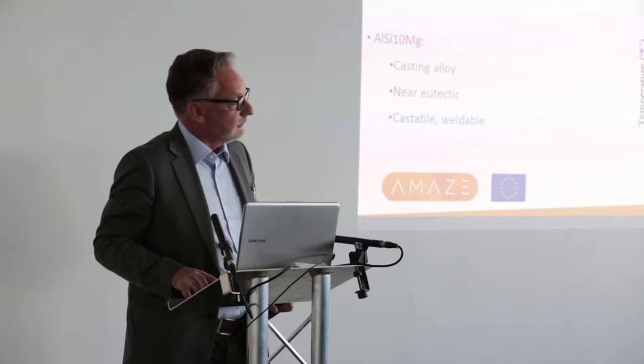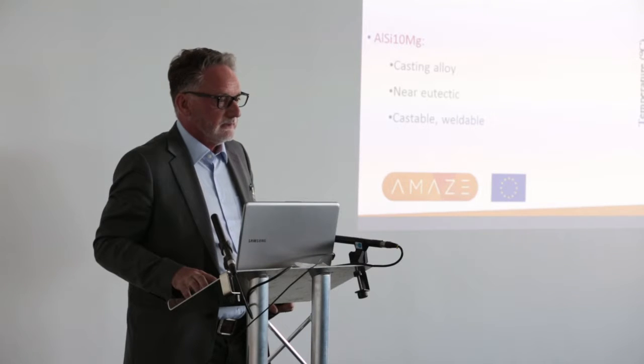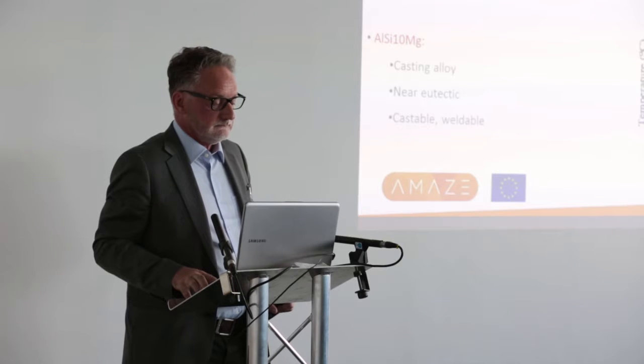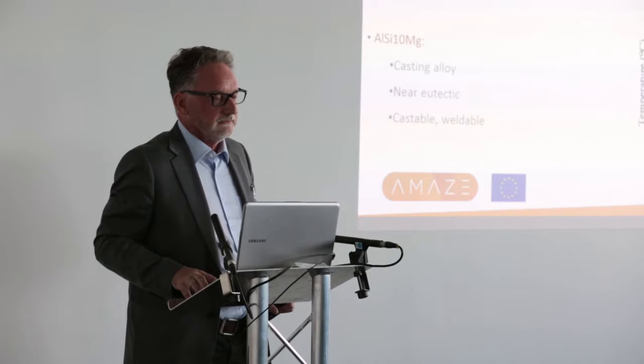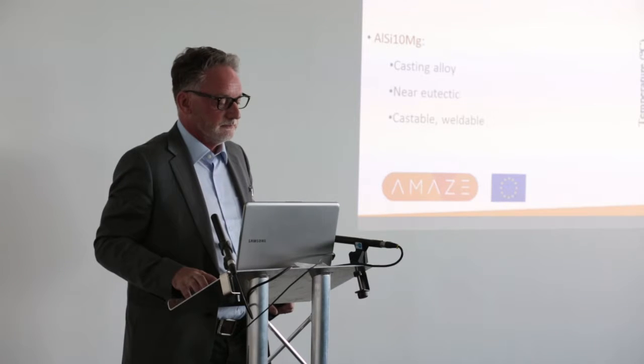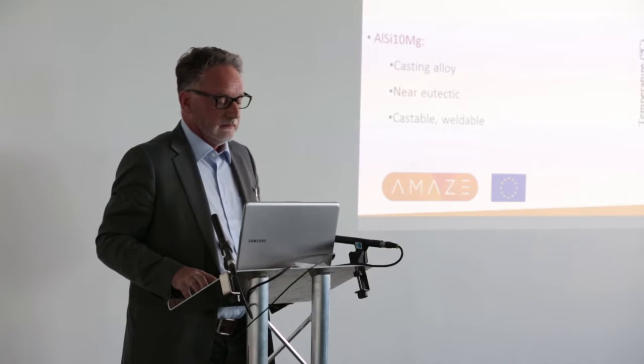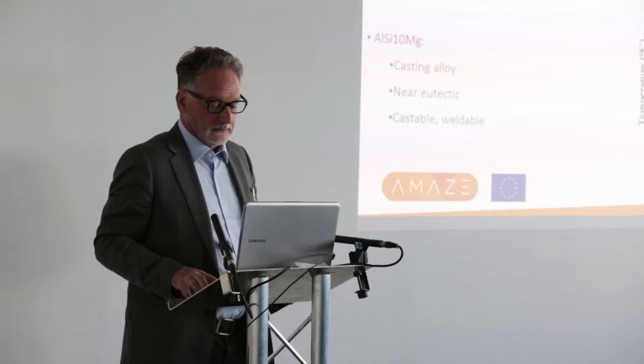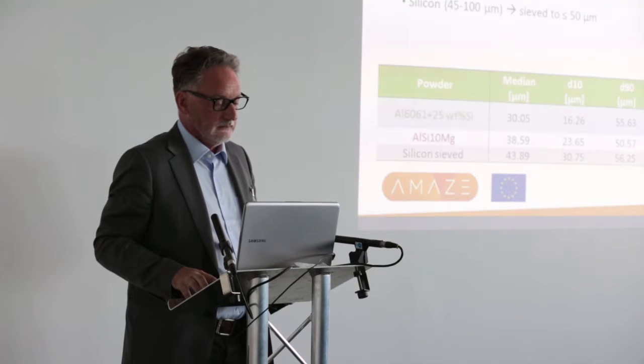So to talk about the work we did, we started with two different base alloys. One was aluminium 6061, which is quite a high strength alloy, and was the first selection in order to produce a very good material. And then we also used the standard aluminium silicon 10 material, because that turned out to be quite a lot easier to process.